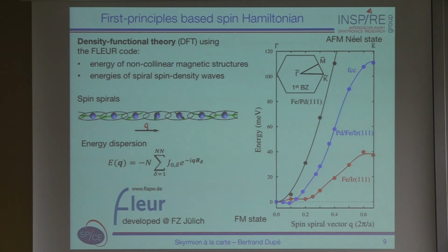DFT is very powerful at calculating homogeneous states. It can be collinear homogeneous states or non-collinear homogeneous states. And these spin spirals are homogeneously rotating, and they are characterized by a propagation vector q. Here, the angle between two nearest neighbor spins is constant. So if you do the Fourier transform of that, it's very well defined in reciprocal space, which is where we are doing our DFT calculations.